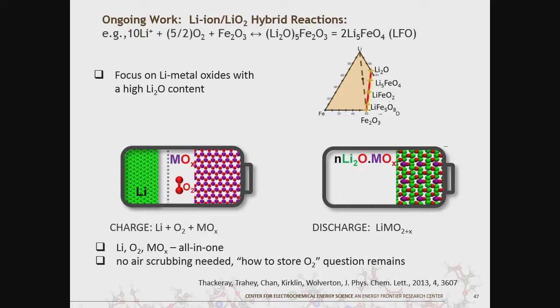What you can see here is kind of an interesting characteristic of this material, which is that there's a series of thermodynamically stable phases that connect hematite down here with lithium oxide over here. So if you look at this reaction written here, you can write the final product as a mixture, basically, of lithium oxide units and hematite units for each of these phases that interconnect these two end regimes.